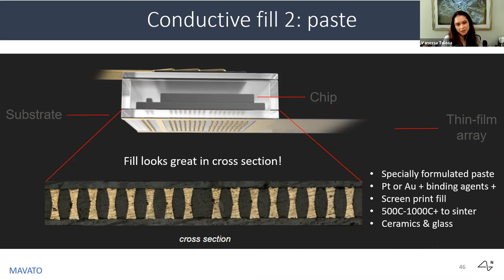You have to partially fill the hole with your paste and then stop, and sinter it at very high temperatures. It can be as high as 1000 C, depending on your materials. You're doing this iterative process because you're trying to degas and burn off any binding agents that are in the paste. And remember, you don't want any voids in your via because it needs to be hermetic. But you get the process worked out and you get a cross-section image and find out that the fill looks great. This is, as I said, an actual image from a real sample.